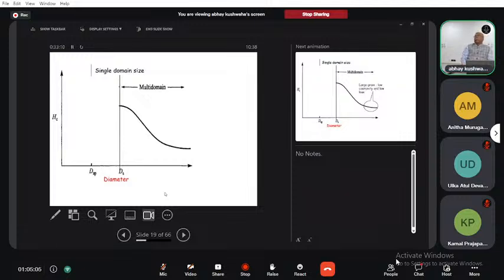Now, another thing that is observed is the grain size. If we plot the grain size and the coercivity of this material, for higher and higher grain size, your coercivity will be as low as possible. And there is a region which is called the Ds diameter, which is the single domain size, and in the single domain size our coercivity is as high as possible. So one condition for hard magnetic materials is that if we can make the domain size comparable to the grain size, then the material Hc will be high. That is the criterion for hard magnets.